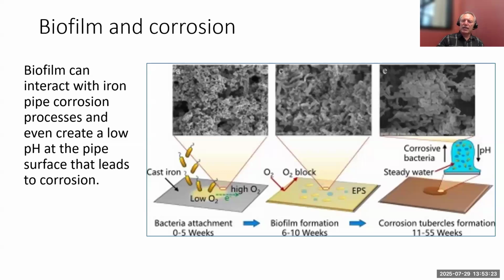And so biofilm interacts with different types of pipes in different ways. And it can even create a low pH at the pipe surface that ends up leading to corrosion. And it can also help to form tubercles. What you're seeing here on the image is different stages in biofilm growth. You see the bacteria attaching and beginning to grow in the first slide. In the middle slide, you see the biofilm is fully forming within 6 to 10 weeks. And then after that, bacteria can break off of that biofilm and begin growing in other parts of the distribution system, but it can also begin to help the corrosion process to do things like pitting and forming tubercles.